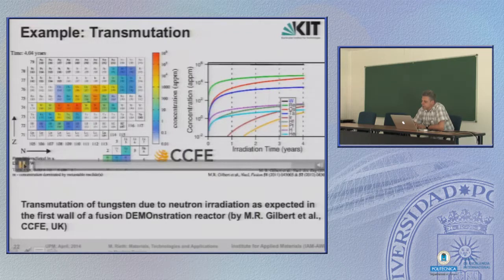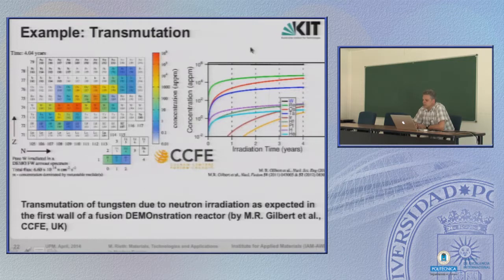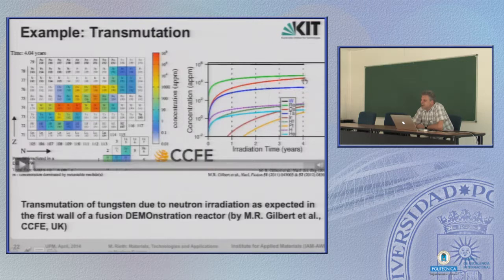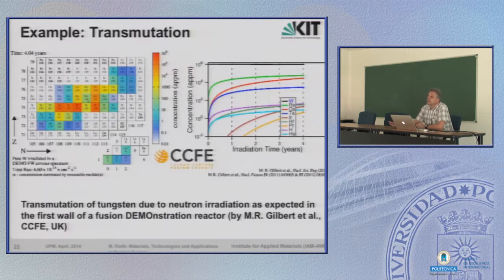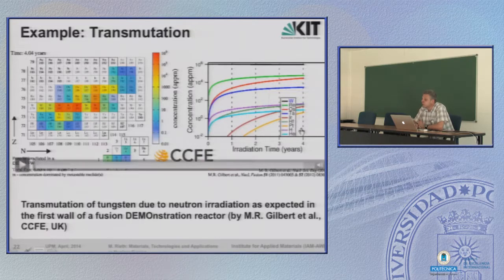It's a bit tricky, but well, you can imagine after 5 years, a lot of rhenium, that's the green line, and also a lot of osmium is produced. So you end up not with pure tungsten, but with a tungsten mix of osmium, rhenium, tantalum, iridium, hafnium, platinum, but also hydrogen and helium. That's the effect of transmutation.